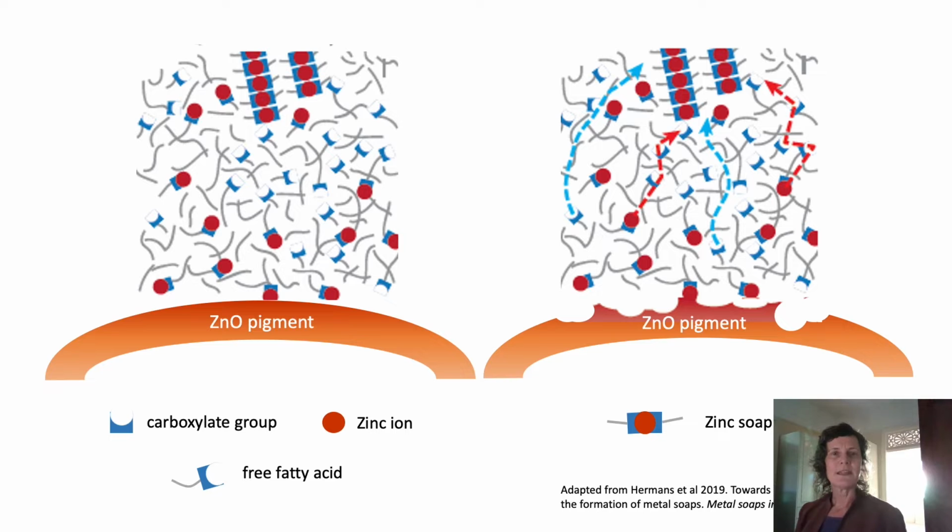The transfer of zinc ions from the network to free fatty acids creates vacant carboxylate sites in the oil binder, and these in turn pull more zinc ions from the pigment. In effect, the zinc oxide progressively dissolves into the oil medium. As the concentration of zinc carboxylates increases in the paint, the mobile chains are drawn to one another and begin to crystallize as zinc soaps. It is in crystalline form that deterioration attributable to zinc soaps in paintings most typically occurs.